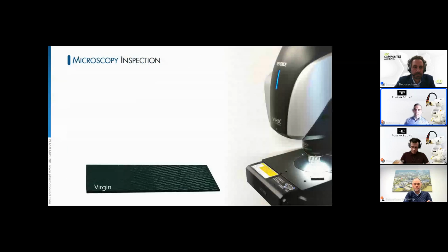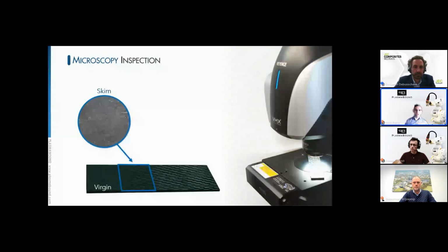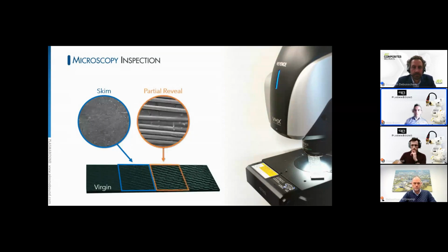So I mentioned in the previous slide that the level of removal can be tailored, exposing more or less of the fibers as required. This is demonstrated here at 3 levels with a coupon at the bottom of the slide. First, we have the virgin on the left. Then we have what we call internally the skim, where there's a little bit of polymer removal, but minimal fiber exposure. So essentially, we're retaining the upper surface or structure, and we're just reducing the amount of weak polymer present at the interface. Then second to this is partial removal or reveal, where the fiber tips are exposed, but they're still infused in the fiber structure themselves. So they're ready to be utilized or engaged in the bond joint, but they're not overly exposed.